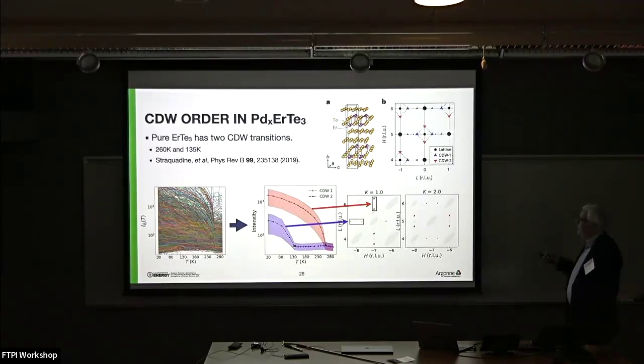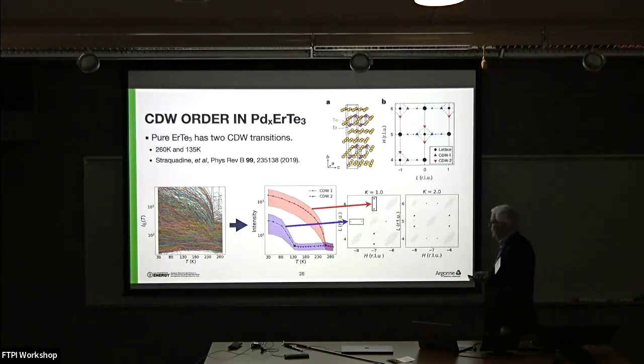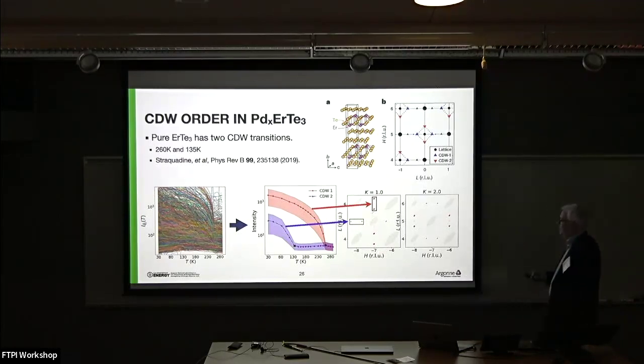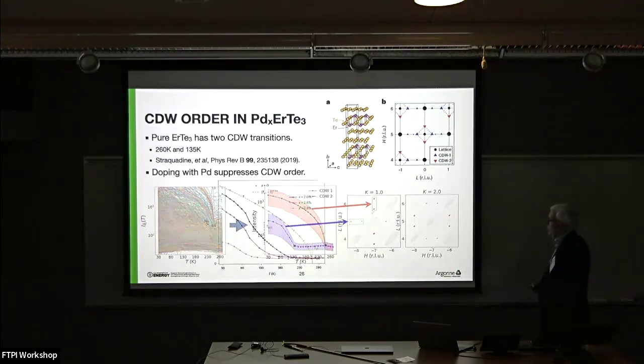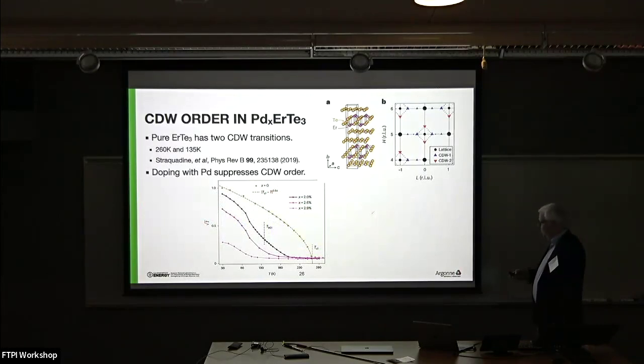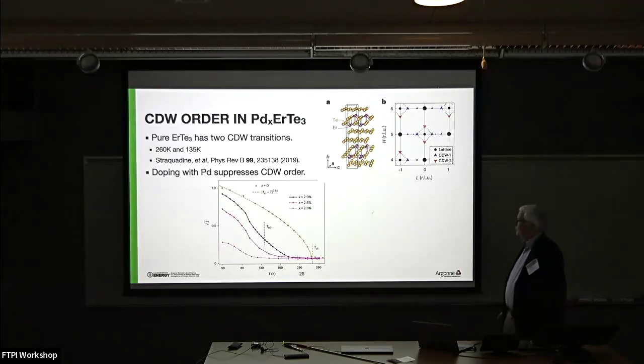You have these square planar bar layers of tellurium, but the square planar actually thin. And so you get, it's all orthorhombic, firstly a CDW along one direction, then at lower temperature, an orthogonal CDW. And doping with palladium suppresses the CDW order. You only have a really nice order parameter for the pristine compound, and if you dope you get some rather weird looking order parameter functions.